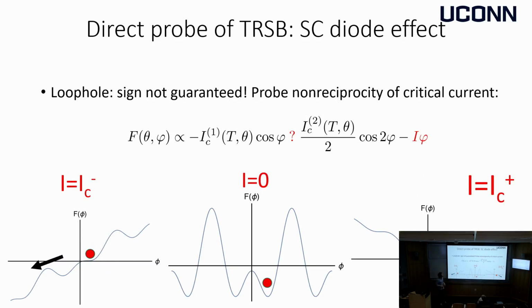The idea is the so-called superconducting diode effect, that we will apply the current to the system, which actually biases this potential. And if we're in a situation where the system chooses one of the symmetry breaking states and will bias the potential to the left or to the right, we will see a different value of the critical current where this potential will become essentially unstable. So if we bias it to the left, you can see that actually the phase will start rolling out of its minimum earlier than when you go to the right. Well, you have to overcome a much bigger potential barrier.